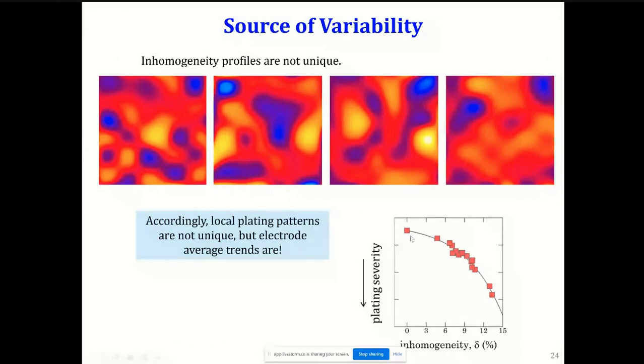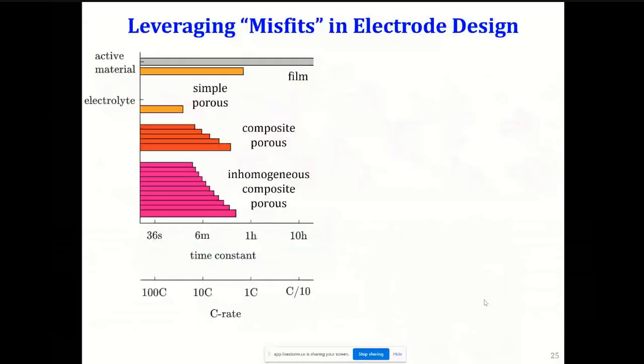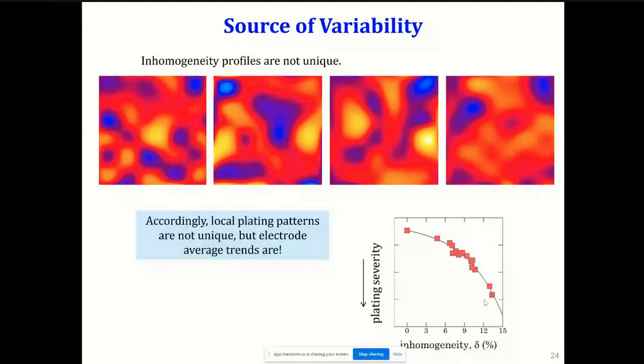The electrode average information is still valid, and that scales with the inhomogeneity. So the amount of disparity between the highest active material packing and the lowest active material packing would decide how extensive or how severe this plating is going to look, right? So there are these variabilities, but that doesn't limit us, because once we put them into our understanding, they let us come up with reasonable ways of approaching these problems, right?